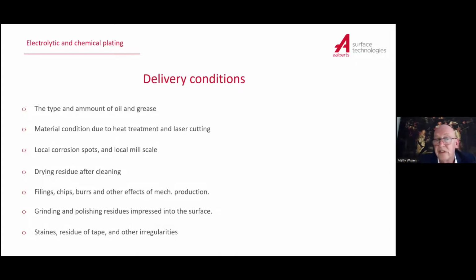Grinding and polishing residues are the same. And one which is very dangerous, and which normally you can't do much about, only be aware, is tape residues. If you talk about axles and rollers, they come in bulk, taped together. You remove the tapes, you treat it, you mechanically make it in order, you send it to us. The tape is gone, but if we pre-treat it, the glue residues make sure that your part is not covered completely. So that's something we have to take care of.